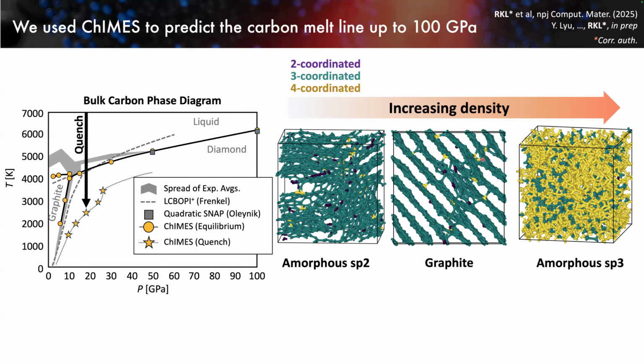And so again, in these simulations, we've got amorphous sp2 carbon, we've got graphite. In this simulation, you can see we're starting to nucleate diamond over here. But if you take all of our data, we find that this equilibrium graphite diamond phase boundary can be pushed out to about where these stars are. So you can form graphite at pressures as high as 25 GPa, depending on how you do that phase transformation.